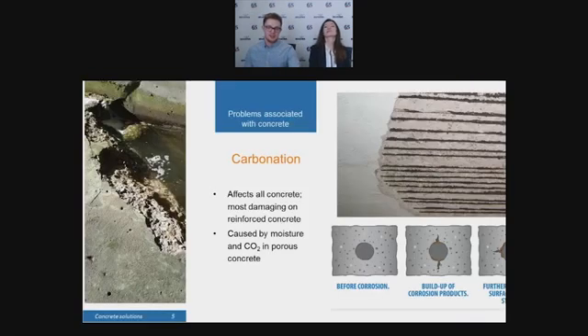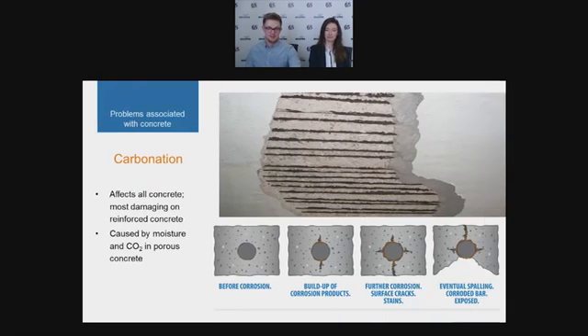Again, sticking with the moisture theme, carbonation is a massive problem throughout industry. It affects pretty much all types of concrete, regardless of where it is, but it's the most damaging on reinforced concrete. What we mean by reinforced concrete is any concrete which has a structural rebar or steel going through the centre of it to give it that extra structural capability. This is caused mainly by moisture and CO2 absorbing through the pores of the concrete and getting down to the rebar. Now, concrete is normally quite alkaline in nature, and what you find is that the passivate layer that sits on the top stops the corrosion from happening.